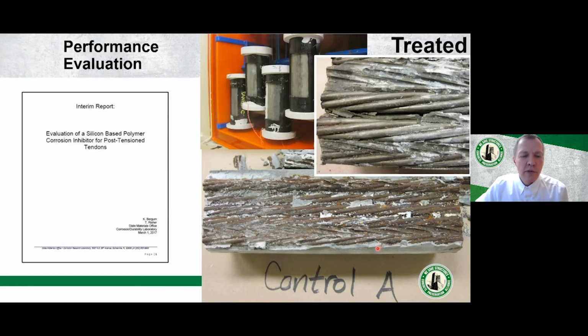Finally, with regard to performance evaluation, I just wanted to show you the front cover of a report that Florida DOT issued. They did some testing, they made samples, and the photos here on the right are from the report. So they had treated and control samples, as they call them, that were exposed to hot salt fog conditions, and also exposed to saltwater ponding. And then after the end of the testing, they broke the samples apart.